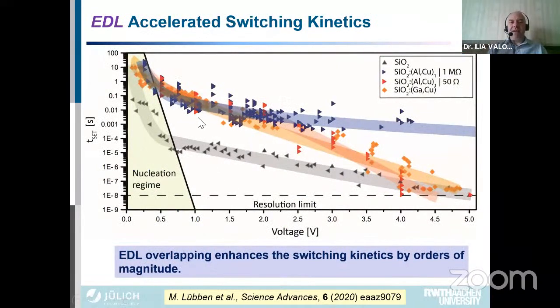Just to show you the effect of impurities, of doping and using different materials. This is a pure silicon oxide we have used as a switching matrix, and this is doped by different materials. At the same voltage, you have orders of magnitude faster switching in materials with doping and a higher concentration of mobile charges compared with almost no additional charges. So it's orders of magnitude.